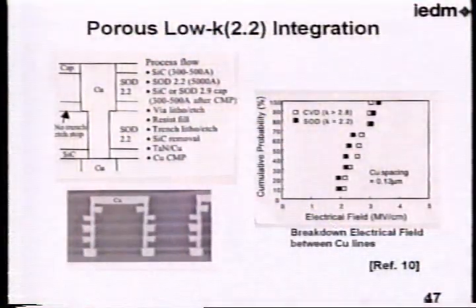So along with this kind of approach, still the conventional single resist process should be investigated. Recently, there is some integration of porous low K MSQ. K value of 2.2 has been demonstrated in the last VLSI symposium. In that case, SOD film K value of 2.2, and this kind of 6-level copper interconnect has been demonstrated. And the breakdown electrical field between coppers is almost similar with the conventional process. So there are many problems with porous materials, but this kind of integration work has recently much progressed.